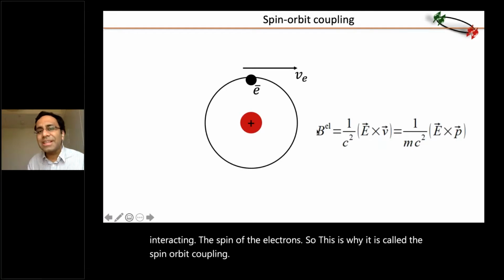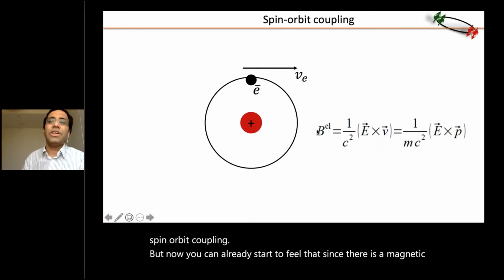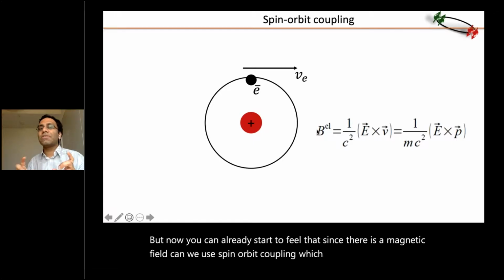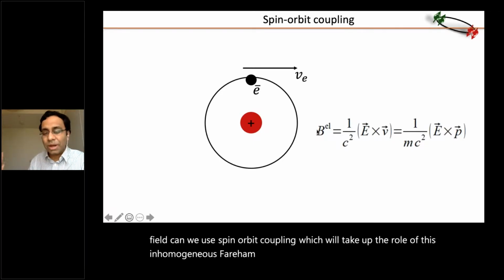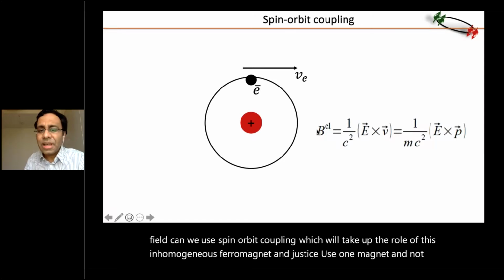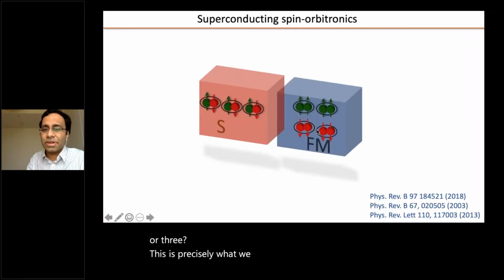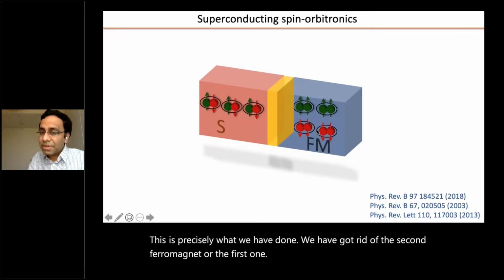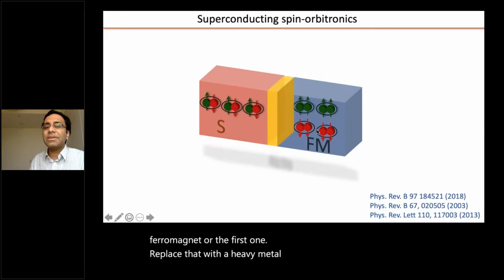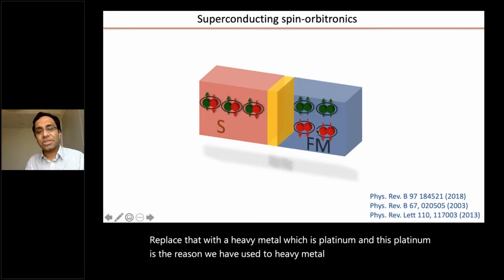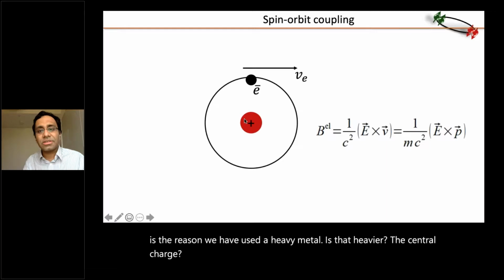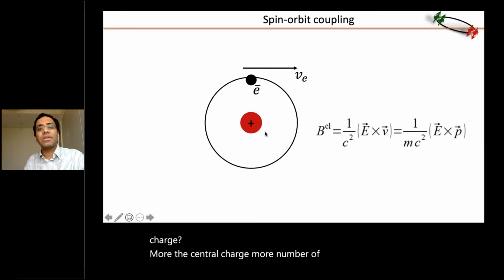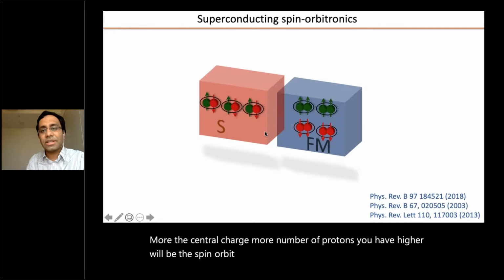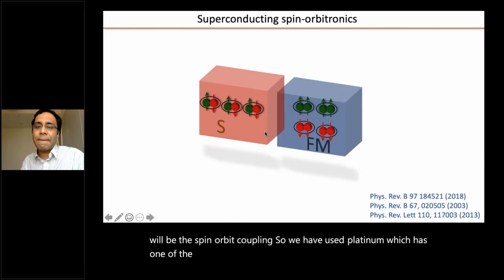But now you can already start to feel that since there is a magnetic field, can we use spin-orbit coupling, which will take up the role of this inhomogeneous ferromagnet, and just use one magnet and not 2 or 3? This is precisely what we have done. We have got rid of the second ferromagnet, or the first one, and replaced that with a heavy metal, which is platinum. The reason we have used a heavy metal is that the heavier the central charge, the more protons you have, the higher the spin-orbit coupling will be. So we have used platinum, which has one of the highest spin-orbit couplings.